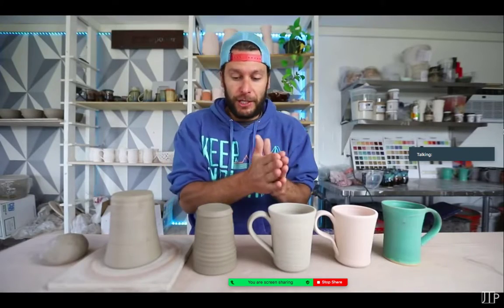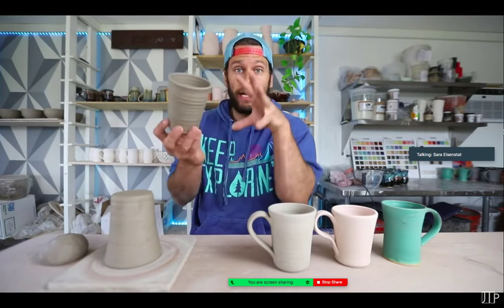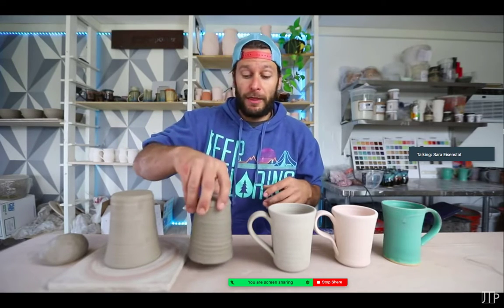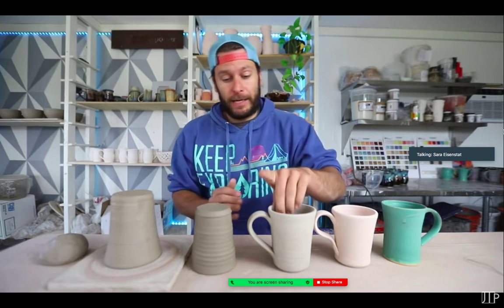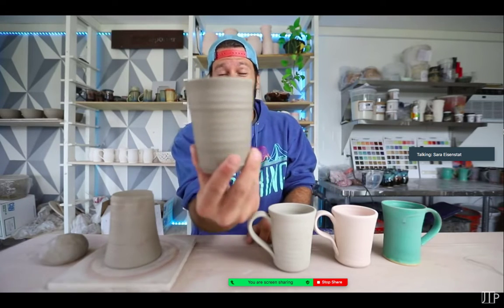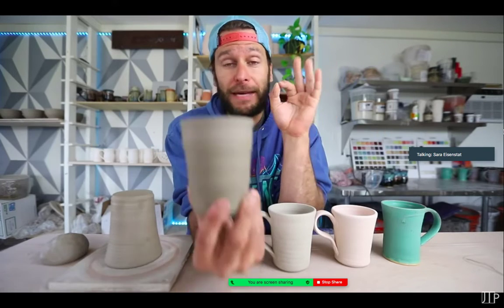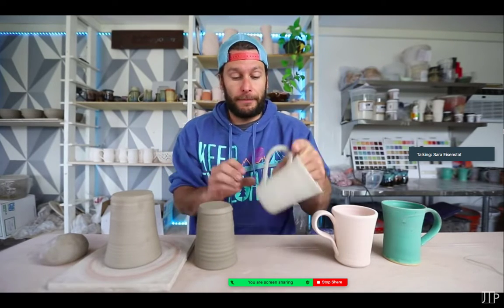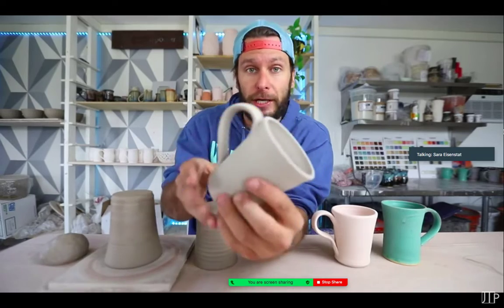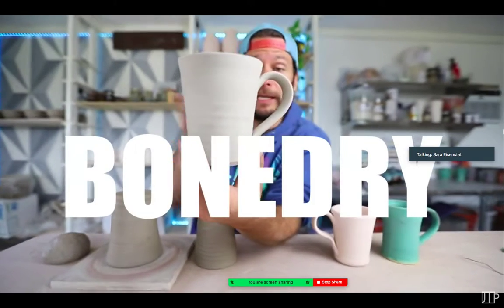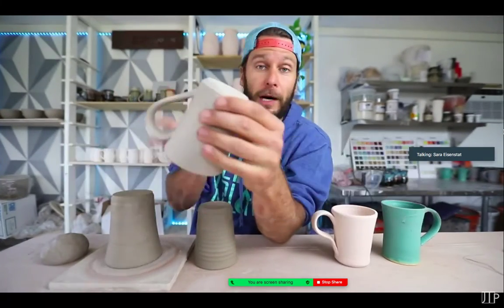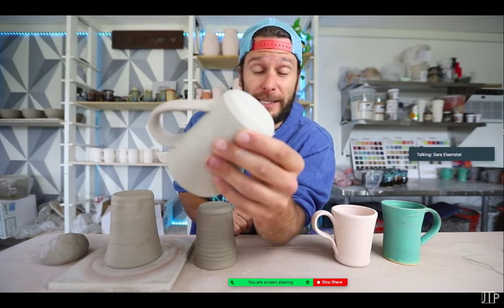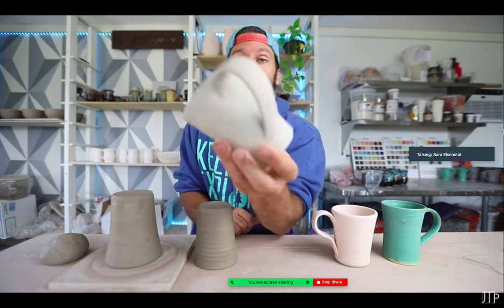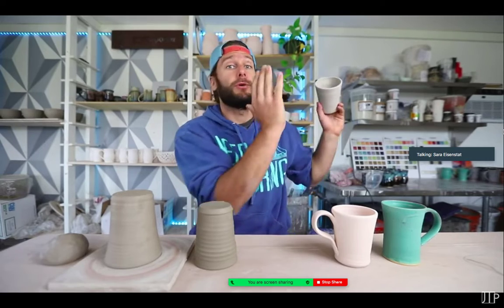The next stage after this, after you put the handle on and you trim it like you saw, is you let it dry. This still has moisture in it, but you can't bisque fire it. Bisque is the term for the first firing. And you can't bisque fire it until it's completely dry, right? Because you don't want any moisture in it. So this is what it looks like when it's completely bone dry. This mug I made like 4 or 5 days ago. It's been sitting, and so it's completely dry. It's ready to get loaded into the bisque fire.